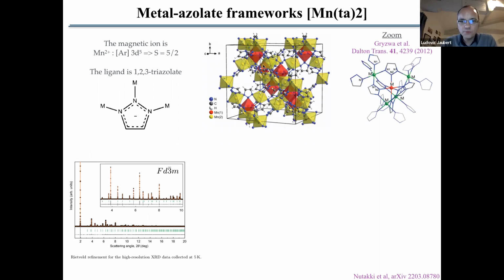But if you zoom in at one corner here, you can see that you have one manganese ion in the middle, and you have the triazolate frameworks connected there. So the nitrogen 2 is connected to this one, and then the nitrogen 1 is connected to this. And you can see that the green manganese ions form a tetrahedron, and the red one is in the center of this tetrahedron here. So everywhere, the yellow octahedra correspond to these green manganese ions, and the red one here corresponds to this green one here.